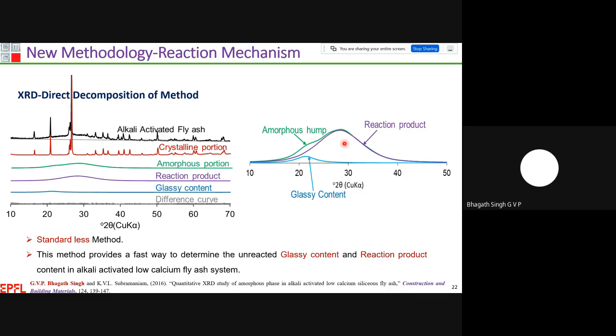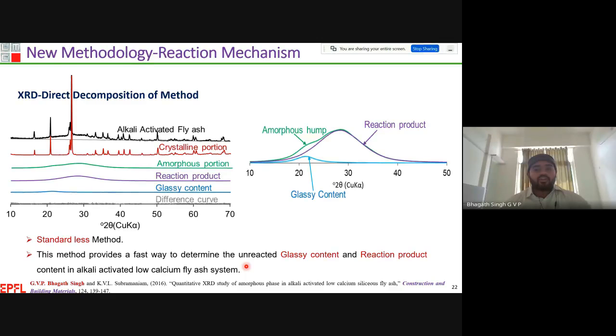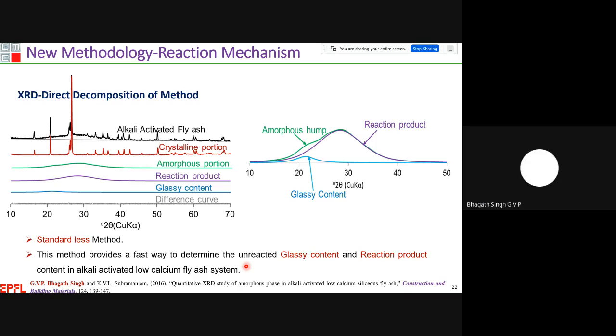And this methodology is a standardless method, does not require any calibration coefficient and other factors, and it requires only the XRD signature of the fly ash and also the alkali activated fly ash. And this method provides a fast way of determining the glassy content and reaction product content in the activation system, and it also helps to predict the reaction kinetics in the alkali activated system.